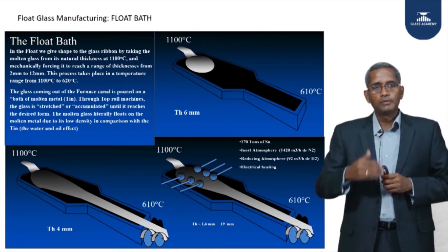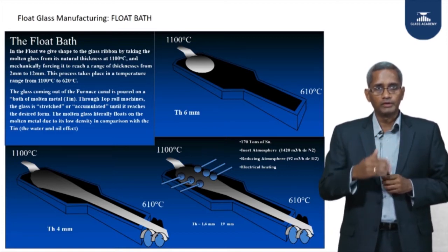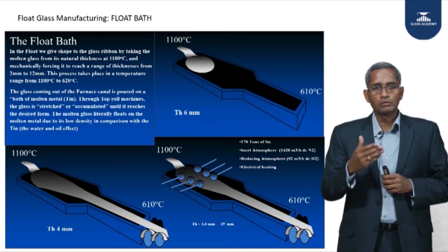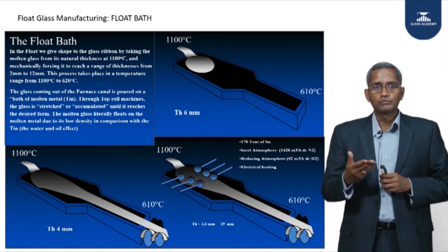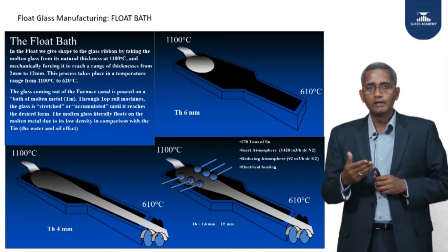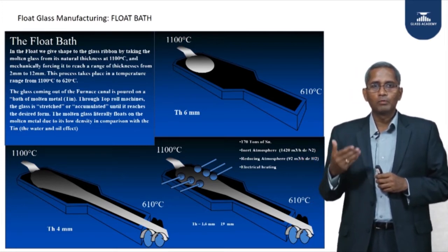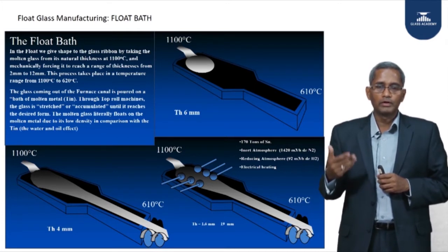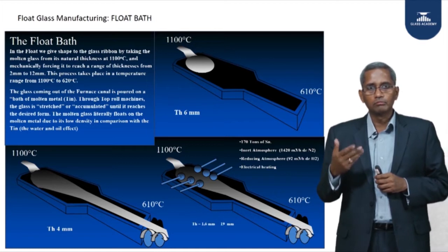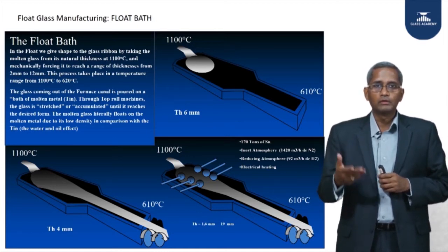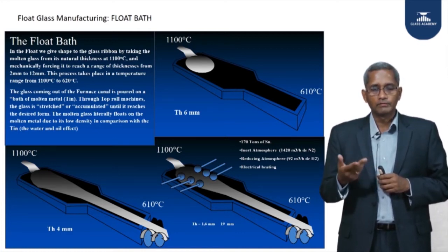The optical properties of the old vertical process were not as good because the glass tended to sag and become wavy. Pilkington brothers thought about the best way to make glass flat. The flattest surface achievable on earth is a liquid surface, so they considered using two immiscible liquids — like oil on water — where if glass floats on top of a molten medium, the thickness and width could be controlled to give a very flat surface.